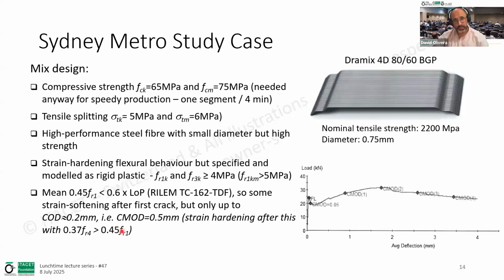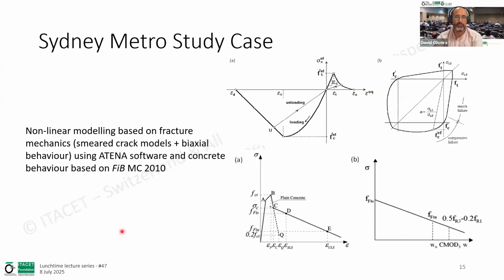So we are happy that we are achieving a very good performance mix, and we decided to also go beyond the linear elastic assumptions and do a full non-linear analysis using more sophisticated concrete modeling based on fracture mechanics. We used smeared crack models with some additions that could allow for biaxial enhancement, and we used Atena concrete software as our tool, and we based our concrete modeling on all the recommendations that exist in the FiB Model Code 2010. So here are some of the constitutive equations and graphs that you can find in more detail in